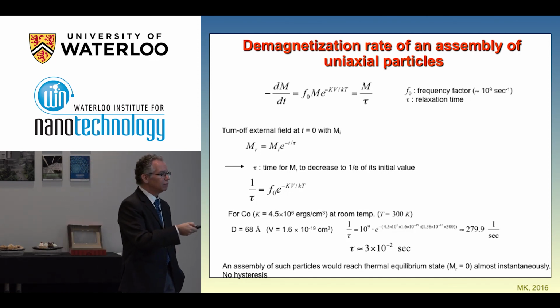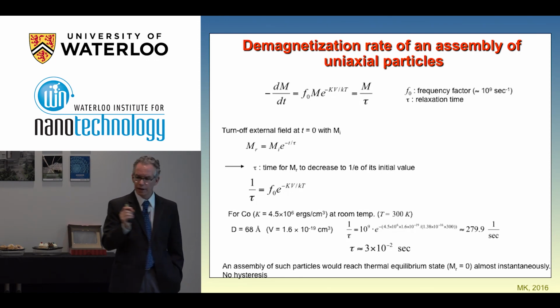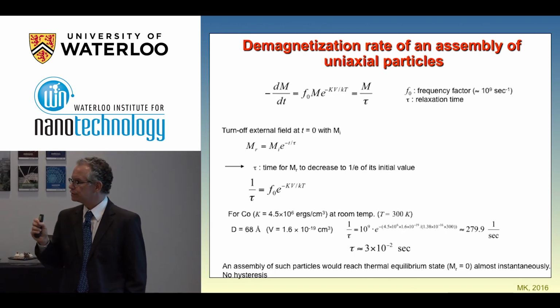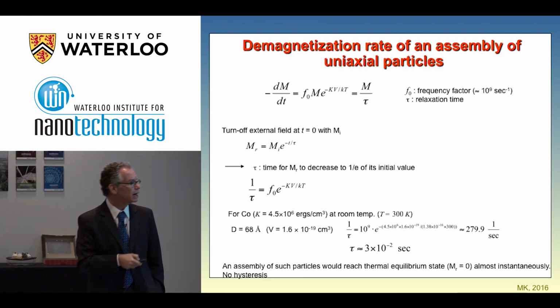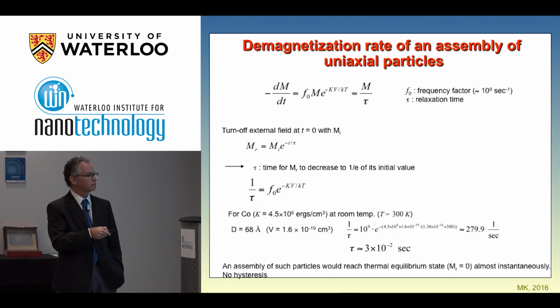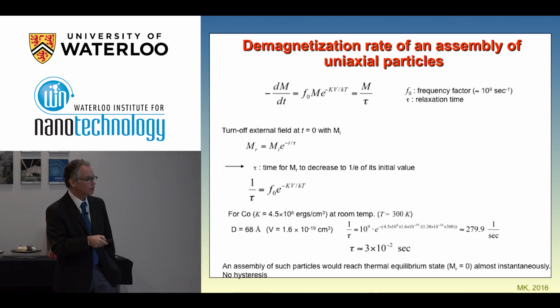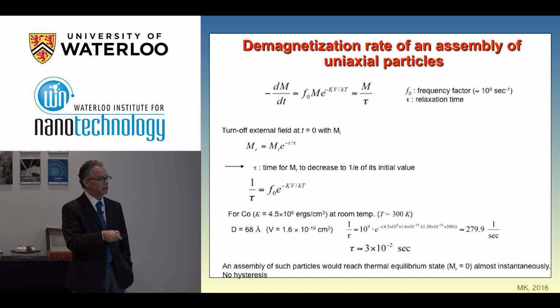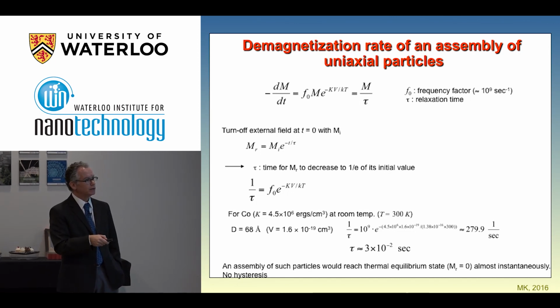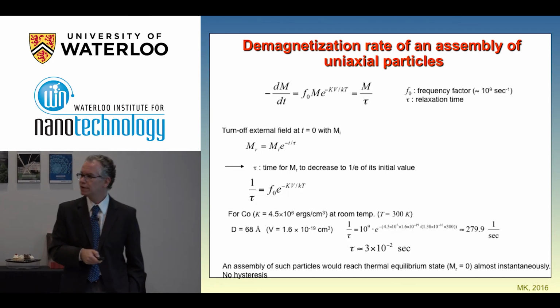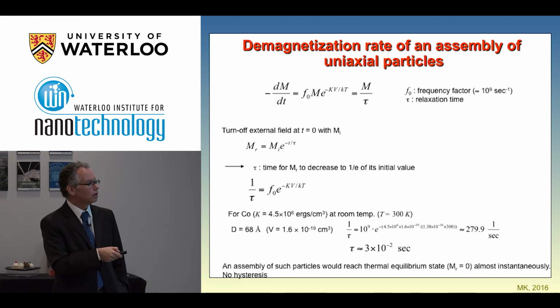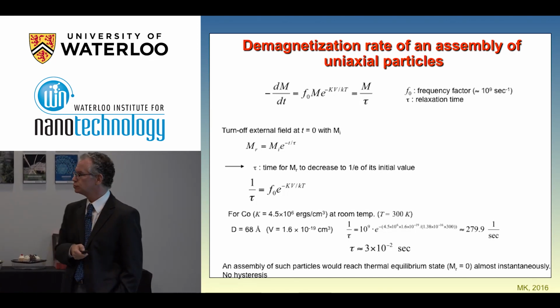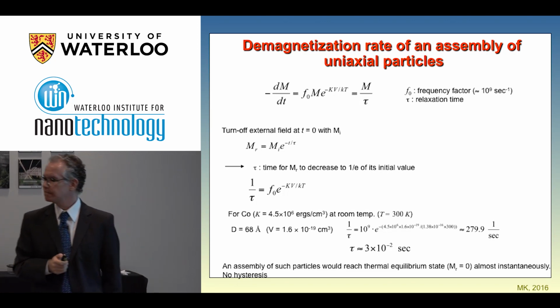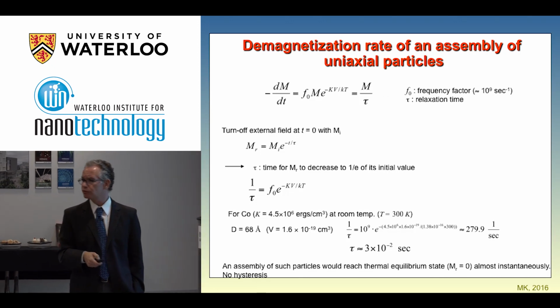I won't go into the detail, but just to mention that in the nanoscopic regime, this is extremely sensitive to the size. Just to mention one example, a particle of cobalt of 68 angstrom, around 7 nanometers, you can have a volume. This is a spherical particle and so on. You can calculate the relaxation time to be around 30 milliseconds. If you take this particle to 80 angstroms, just 1 nanometer larger, this relaxation time goes to 300 years.